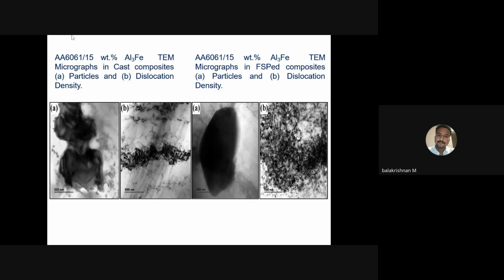Here we can see the particles and dislocation density of the particular particles. The dislocations are not suitable for the enhancement of strength. Therefore, after friction stir processing, the composite particles and dislocation density was improved highly.